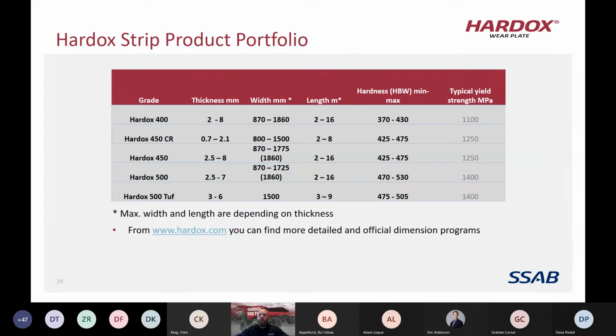We also produce some strip product or coil products. These are much thinner gauges and limited in width, but have very good surface properties, very good flatness and surface finish. We produce anything from a Hardox 400 all the way up through a Hardox 500 Tuf, in varying thicknesses depending on the grade, but anywhere from 2 millimeter up to 8 millimeter. We also have what we call Hardox 450 cold rolled from 0.7 millimeter up to 2.1 millimeter. So we have a wide range of grades and varying thicknesses to cover whatever your needs may possibly be.